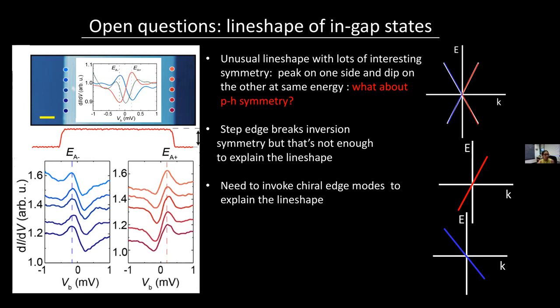A final short question: this asymmetry between the blue and red step edges means mirror symmetry is broken. But it's actually not consistent with what you'd think about a chiral edge state — chiral edge states would preserve mirror times time reversal, so the spectrum should look the same on right and left. It's chiral in the sense that right and left hands are different. But remember, we're looking at step edges where there's broken inversion or mirror symmetry.